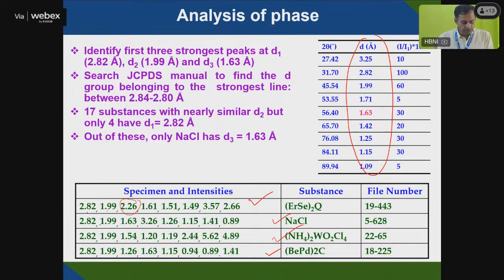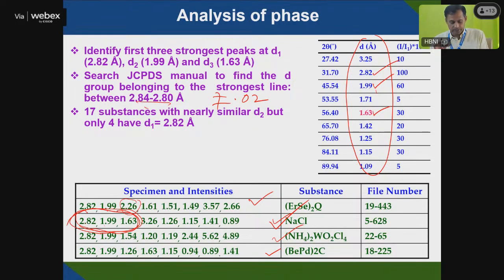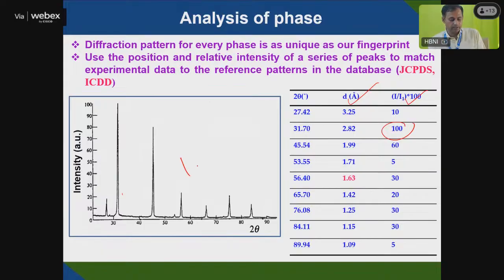So I have to look for the minimum. The second one you see, 2.82, is my most intense, then 1.99, then 1.63. So these three are coming here, and in the other cases they are not coming. This is the set of planes that is coming close to each other. Identify the first three strongest planes, D1, D2 and D3, and search JCPDS manually. There is 2.84 and 2.80 plus or minus 0.02; we have to see that variation. I have got this plane, and since up to the third d-spacing is matching with NaCl, my crystal structure is NaCl. This XRD pattern is nothing but NaCl.